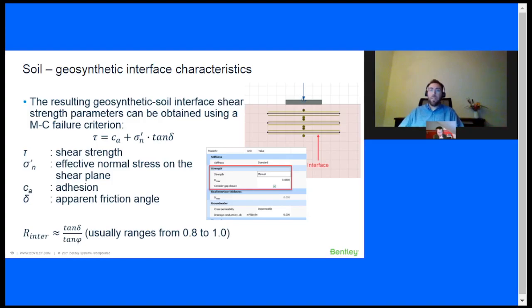Now, in PLAXIS, the shear strength parameters of the interface can be obtained using a Mohr-Coulomb strength failure criterion. However, in this case, instead of a friction angle phi and a cohesion c, the strength parameters are expressed in terms of apparent friction angle, which is delta, and adhesion, Ca. These are parameters which are determined with the tests that we have mentioned earlier. Therefore, the strength reduction factor becomes almost equal to the ratio of tan delta over tan phi, which some of you may already know from geosynthetic design is termed as the efficiency of the geosynthetic.